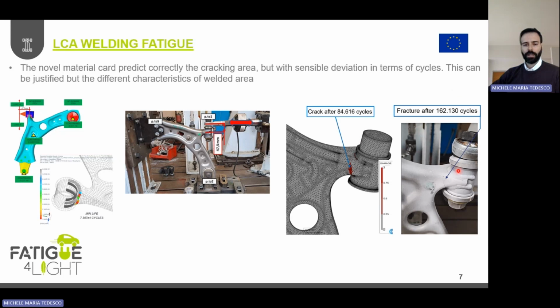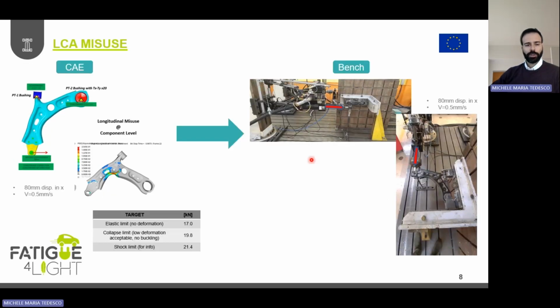The justification of this difference is due to the welding process, because during the arc welding we are heating up the material, and so also the mechanical properties in the area near the welding zone are different. And so it's very difficult to predict this in the FEM simulation. But on that, we are still continuing to work in order to be closer between the simulation and the real life. The last characterization is not a fatigue, but is a misuse.